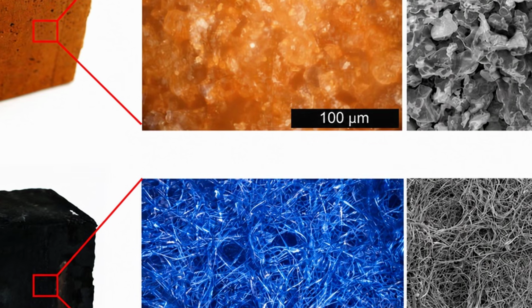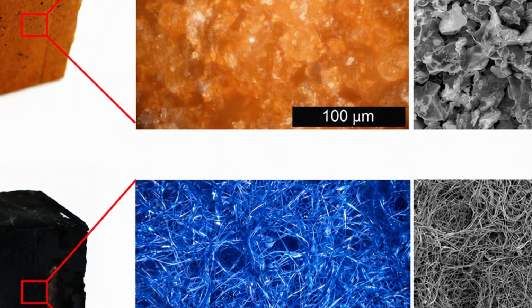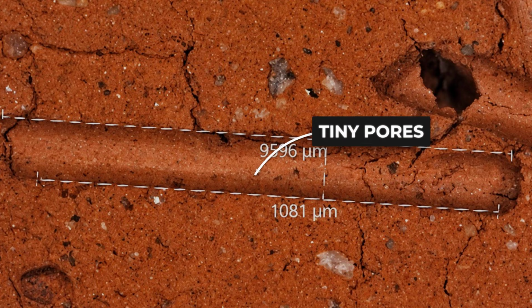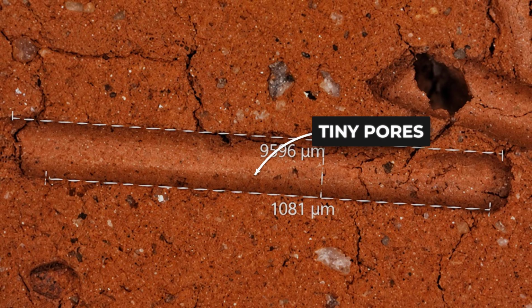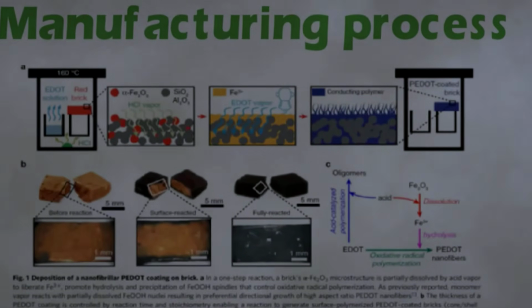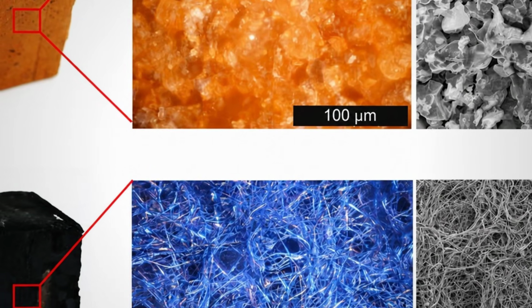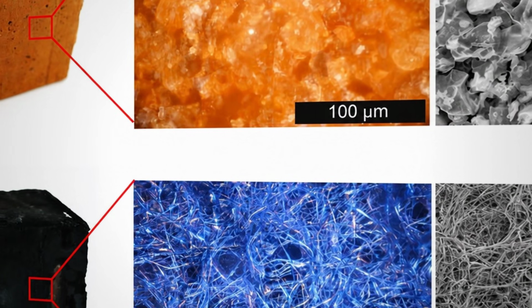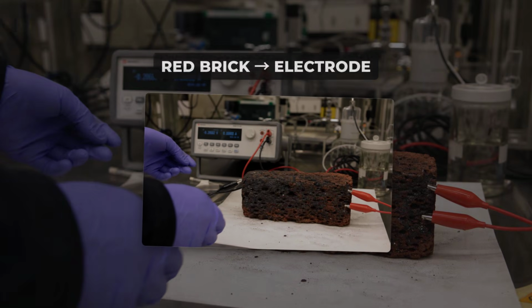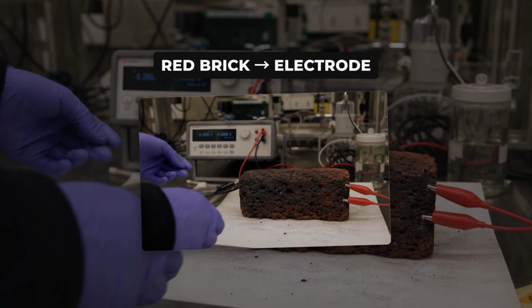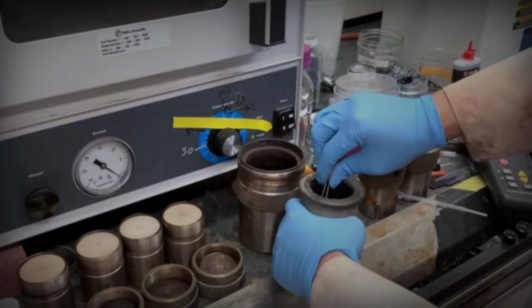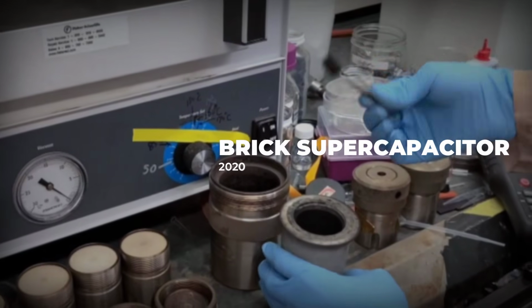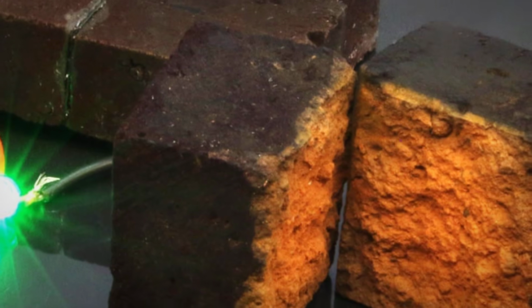Red bricks get their color from iron oxide, the same rust-colored mineral, and they're full of tiny pores like a sponge. Darcy's team pumped acid vapor and a special gas into those pores, and the reaction grew a network of conductive plastic fibers all through the brick. That conductive web turned the brick into an electrode. Pair 2 treated bricks with a gel in between, seal it, and you've got a supercapacitor you can literally build